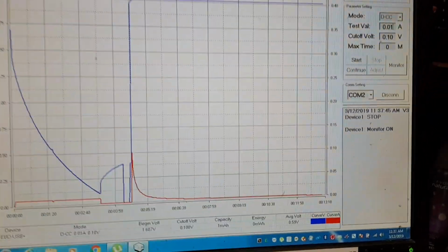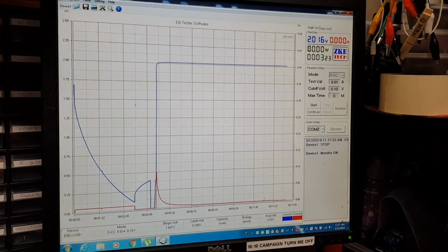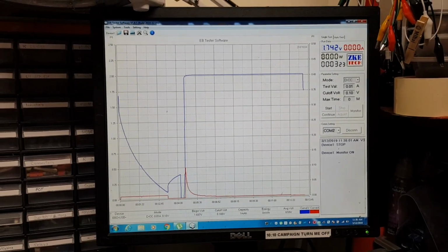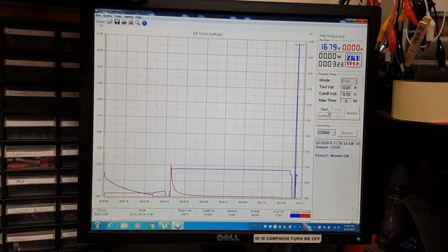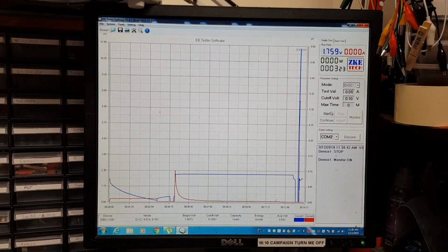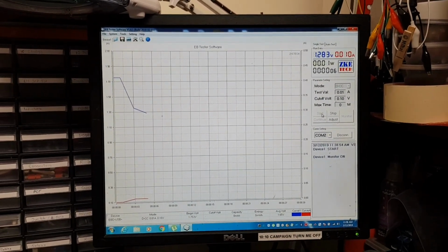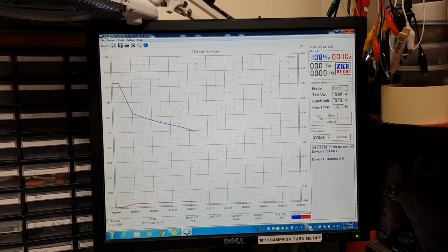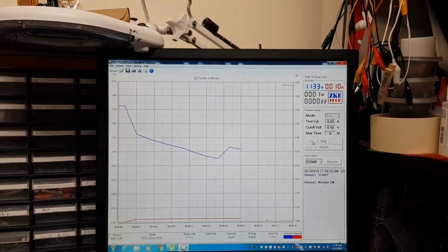Okay, so at around 9 minutes of charging, the current dropped to zero. I'm going to stop now the power supply to see where the voltage will drop. And 1.77, not bad. We'll start to run now the third discharge cycle. Sorry, I keep getting interrupted by the alarm for the microwave. Again dropped substantially. And we will see what will happen. That was interesting.